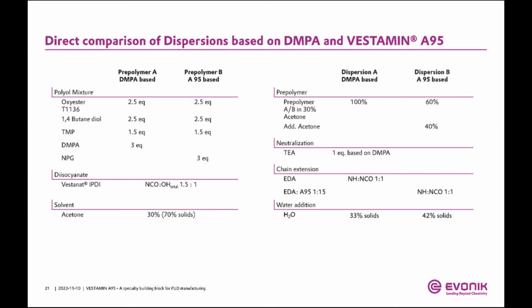What do we do with these prepolymers? The first step, and this is a difference, we have to admit: the dispersion which is based on A95 gets some additional acetone, so we need some more acetone in this case. Maybe this additional step is compensated by the fact that the DMPA-based system needs to be neutralized, as we discussed. This can be skipped, of course, in the case of A95. We already have the salt. We don't start with the acid.